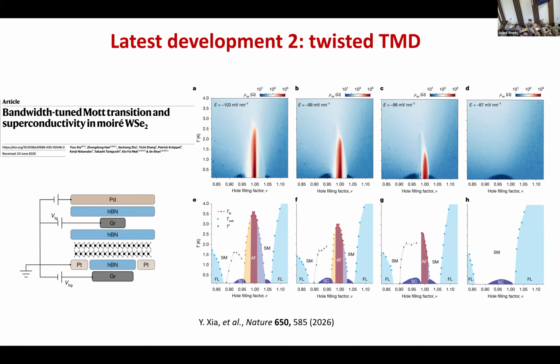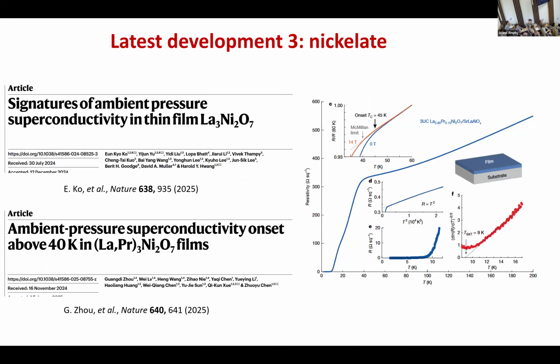And the third development in this field, I think, is about nickelate. This is not particularly 2D, but they have to do a 2D because this so-called 3 to 7 compound, in the single crystal form, you need to have a very high pressure, usually 20 gigapascal, to make it really superconducting. And the transition temperature onset TC could be 70K or even higher.